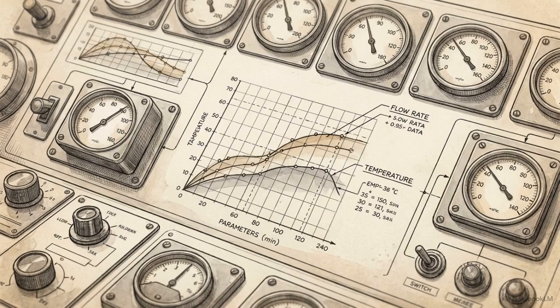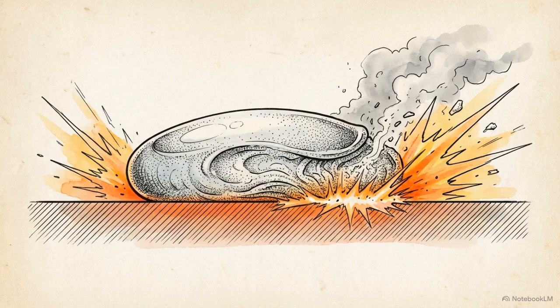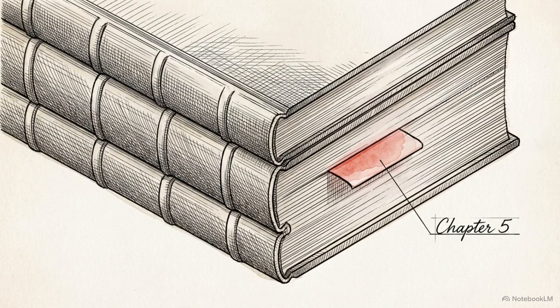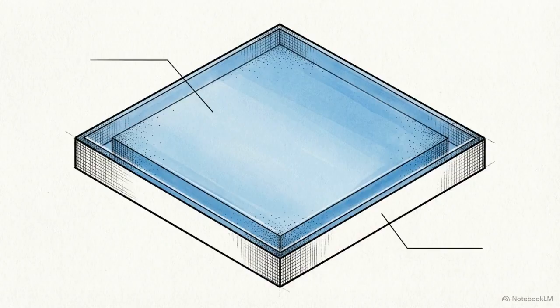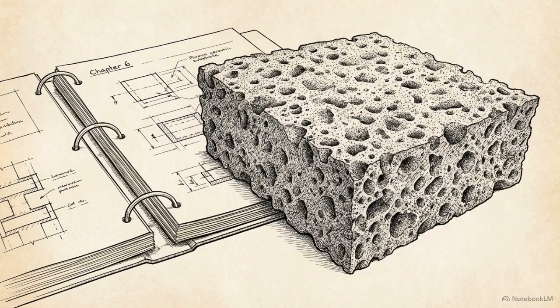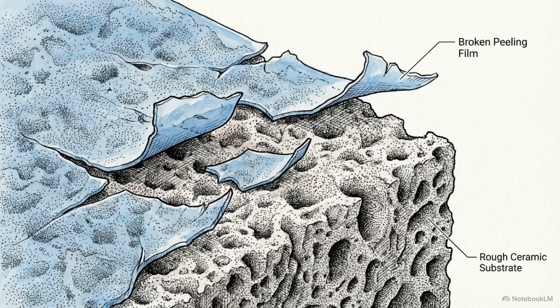Mastering spray pyrolysis requires calculating the exact carrier gas flow rate, the chamber temperature, and the chemical molarity so that thermal decomposition happens precisely at the moment of impact. In early experiments, detailed in Chapter 5 of his thesis, Dr. Chourashiya successfully optimized these parameters by depositing the GDC film onto perfectly smooth glass substrates. However, moving from glass to the actual target material in Chapter 6 immediately broke the process. The exact same spray parameters completely failed when applied to the rough, porous nickel oxide ceramic.